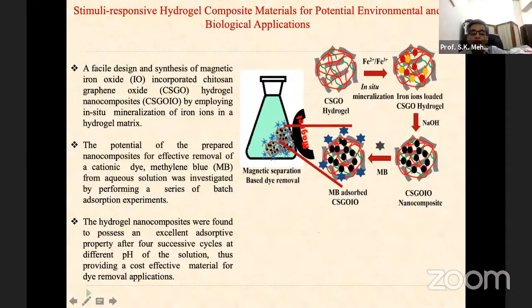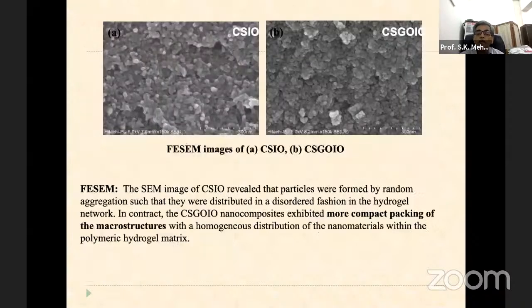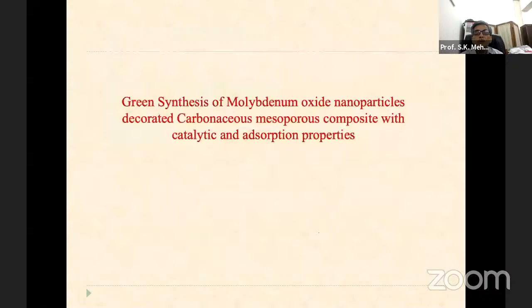We found that this hydrogel nanocomposite possesses excellent adsorbent properties, even after 4 successive cycles at different pH of the solution. So it provides us a cost-effective material for dye removal applications. The other thing is how we reuse it. Once we do the process, we can do magnetic separation. Using a magnet, you can separate the iron particles, and once you separate, you can again do the dye degradation using the same particles. So 4 times this was done, and we found that it is working extensively. Although this hydrogel is also being used for other purposes.